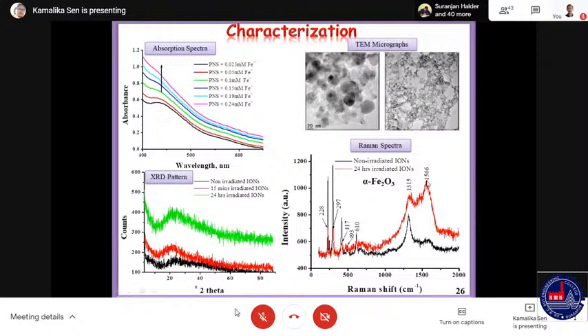A lot of carbonyl groups were present inside the polyphenol, which get bonded with the iron. This happens after the irradiation, because irradiation causes radiolysis of the polyphenol and breakage of some carbonyl groups, which are now getting bonded with the iron, and a metal carbonyl bond is formed after irradiation. And we can see the TEM images.